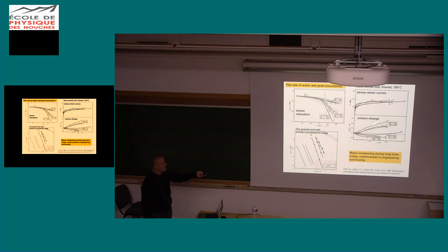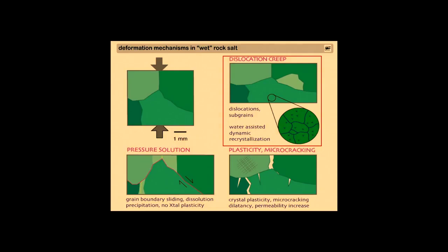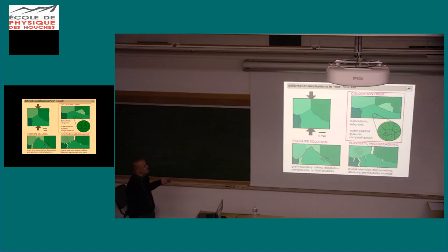The samples that dilated didn't show this. And we have explained that because the samples that dilated couldn't form these grain boundaries, because they dilated and the water could evaporate. So we started looking at dislocation creep with water-assisted dynamic recrystallization at the grain boundaries as a very important process.